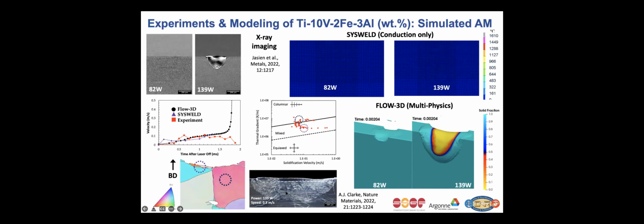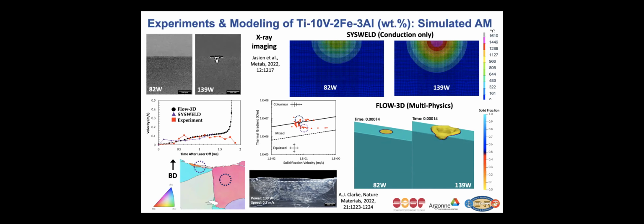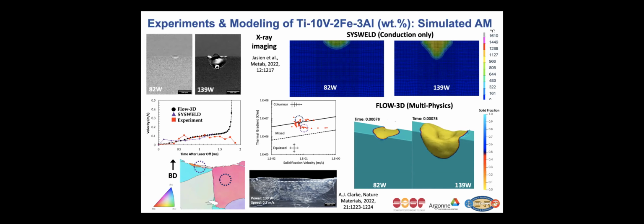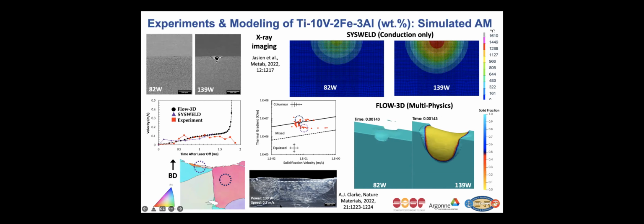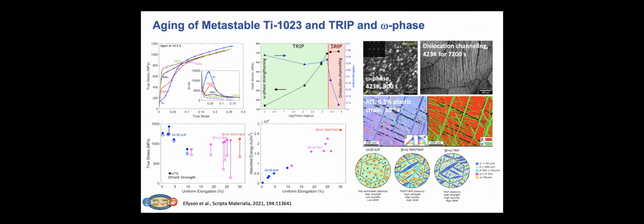So this is pretty neat because it suggests during the laser track melt, we actually are accommodating the residual stress during the build, and it suggests that these types of beta Ti alloys might be more forgiving in terms of the AM build process. And there's really more to understand here in terms of which grains tend to transform and what are the local conditions. And that's something we're currently looking at.